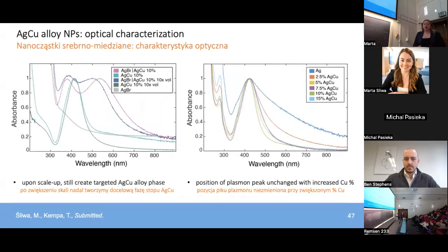We also showed that we can scale up our synthesis and still see that 2-peak dimer profile after exposure to UV and L-arginine, even if we increase the solution volume to 10 times with that reaction volume. And when we etch away the silver bromide, again, recovery of that silver plasmon peak.